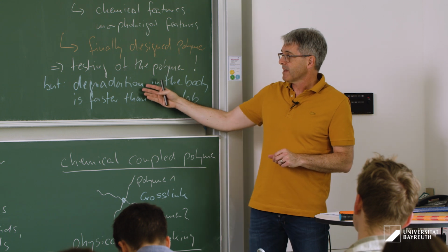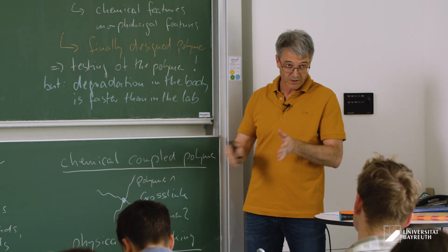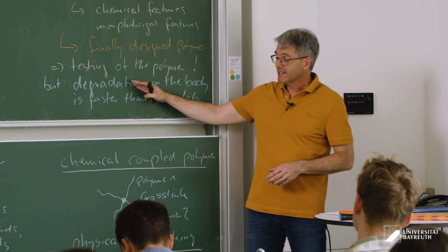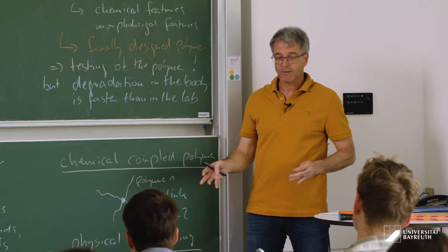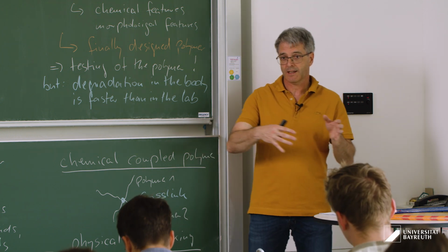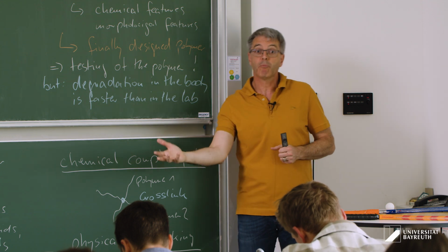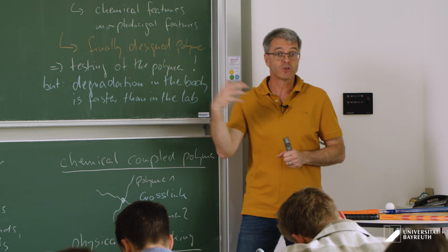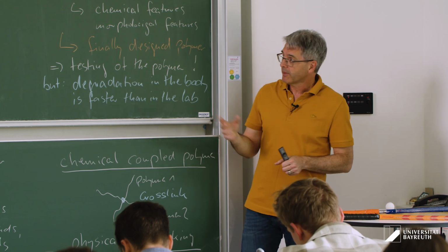And how this is typically done: if you make degradation tests in vitro, so in the laboratory, you actually add a lot more enzymes than will typically occur inside your body. So proteases and stuff. So you overdo it, so to say. You want to speed things up and see what happens under worst case. This is how you typically deal with these issues.